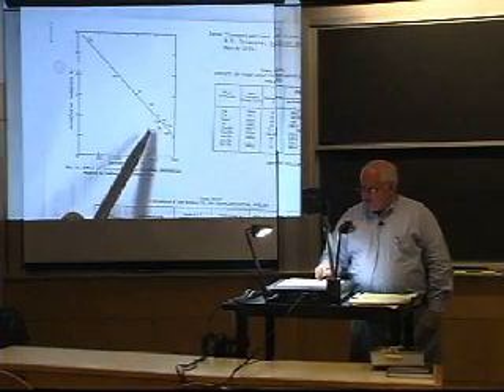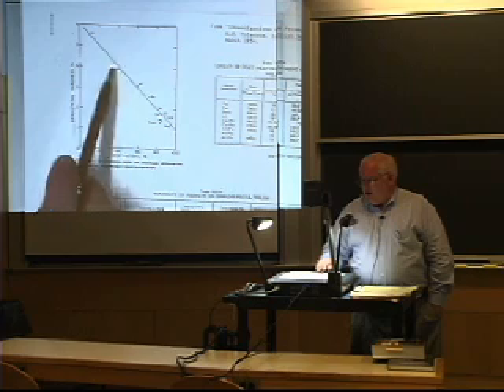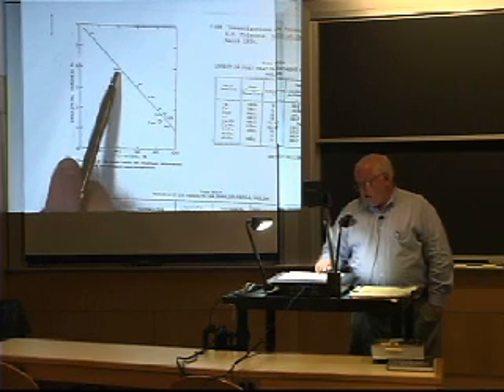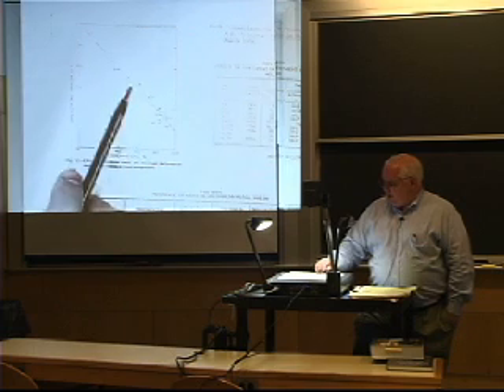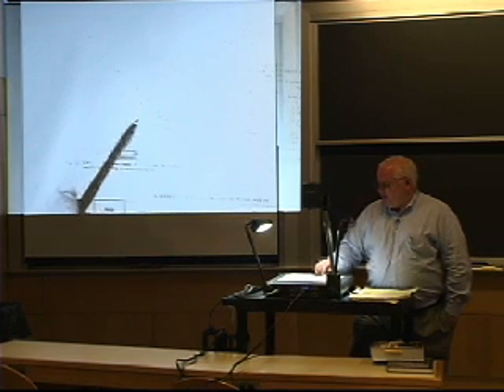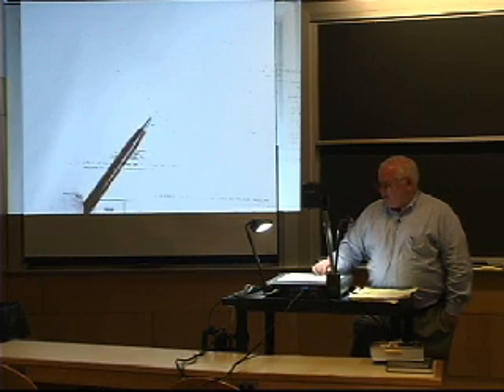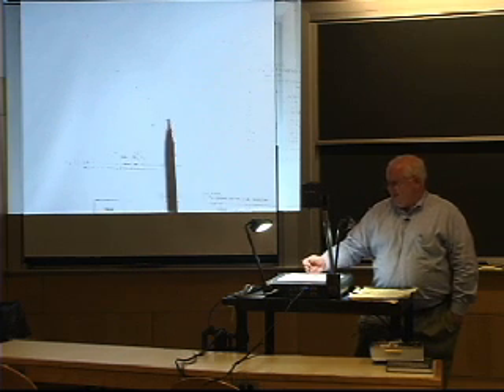Aluminum is also relatively soft compared to some things like nickel alloys or steel or iron-based alloys with a very high hardness oxide. This is relatively pure aluminum. This is aluminum alloy. If you go back and look at the individual data, here's tin and tin oxide, tin soft, and tin oxide is relatively hard. Most of the metals, steels and copper alloys and nickel alloys, more common alloys, it takes 80–90% deformation in order to get a good strong bond.